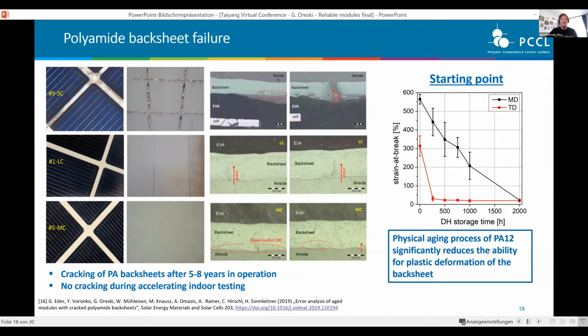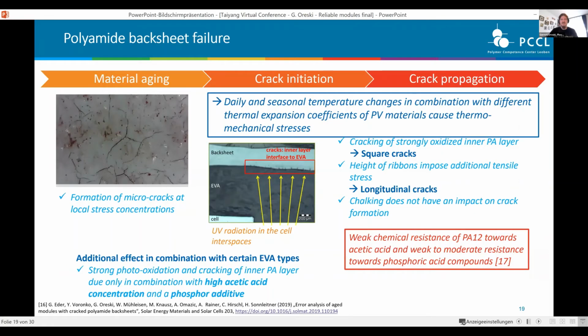Then after some years, obviously we have material aging. So in all cases, we observed formation of microcracks at local stress concentrations. So that was found on every backsheet we investigated so far. In order to get these cracks in between the cells, that was happening only in combination with certain EVA types, where we saw strong photooxidation and cracking from the inside.